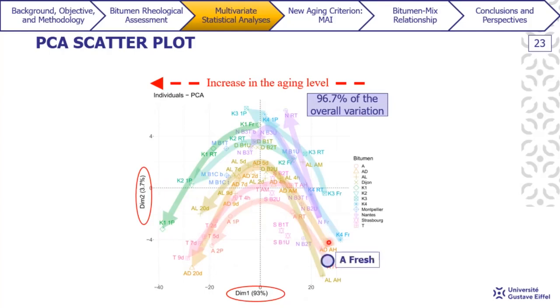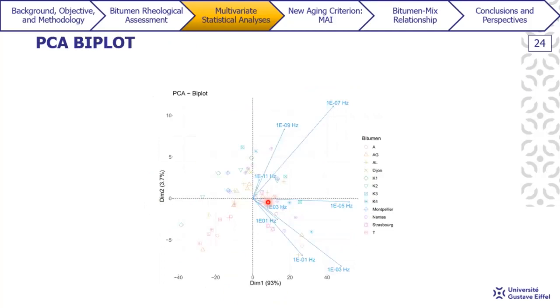So here, just to make clear, I'm just going to highlight all the four aging levels of bitumen A. Here is where we have our fresh bitumen A. Here is the RTFOT aged bitumen A, one PAV and two PAV aged. So we can clearly see this inflection that seems to take place halfway once we cross this vertical axis. So now let's take a look at the PCA biplot to better understand the influence of the original variables on the position of each of these bitumens on the PCA scatter plot.